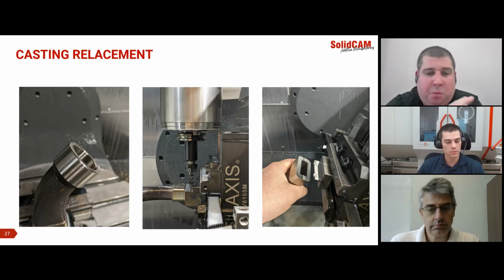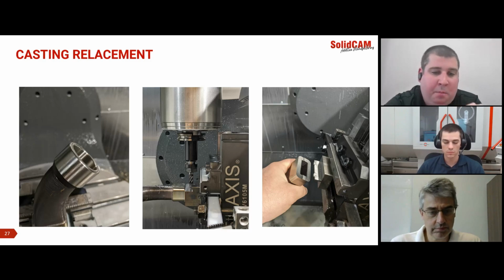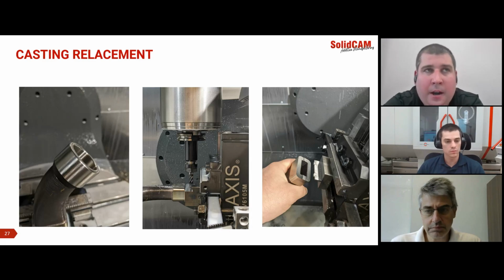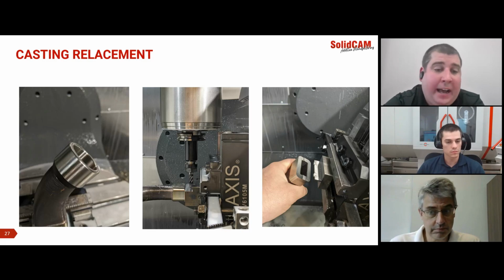So what you would want to do is print between 0 and 15 degrees and then machine from 0 to 10. Then print from 15 to 30, and then you might start machining from 10 to 20. That way you're leaving a standoff distance to provide a thermal barrier and not distort what you've previously machined and not create an overhang condition. So if you're machining up to where you start depositing again, you're going to have some type of overhang condition. And yes, with multi-axis, we can tilt the head to alleviate some of that concern, but you're still going to be fighting that thermal distortion.